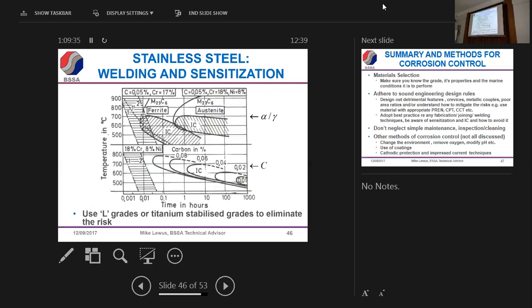If we've got an L grade, with 0.03% carbon, we've suddenly got 10 hours. So you'd have to be a pretty slow welder to keep the material at temperature for 10 hours, so you're on very safe ground.